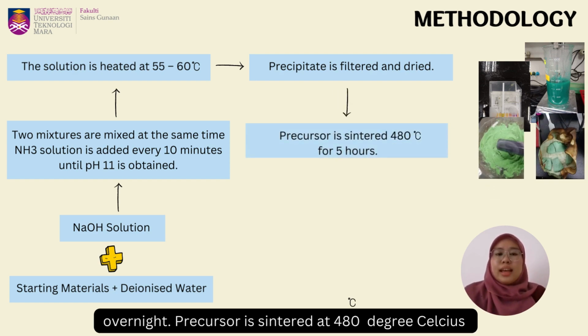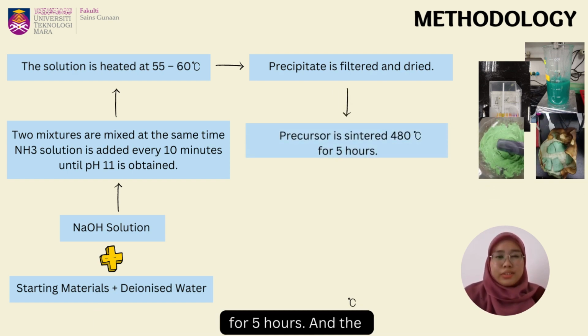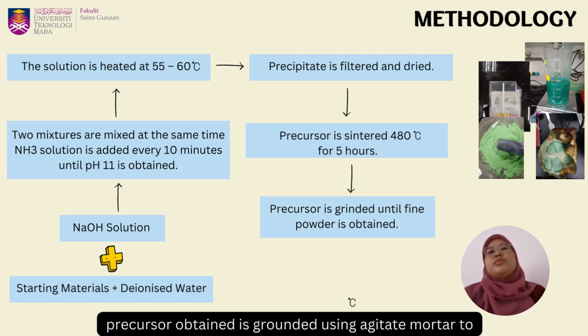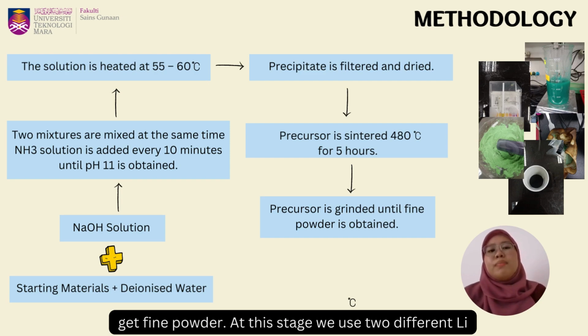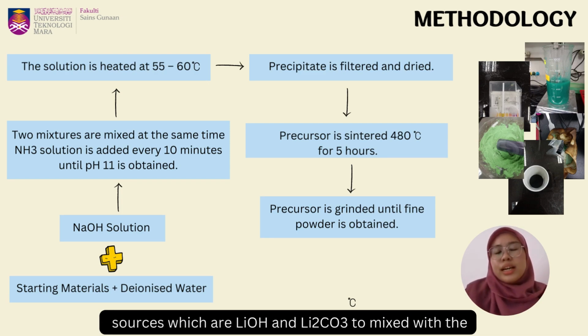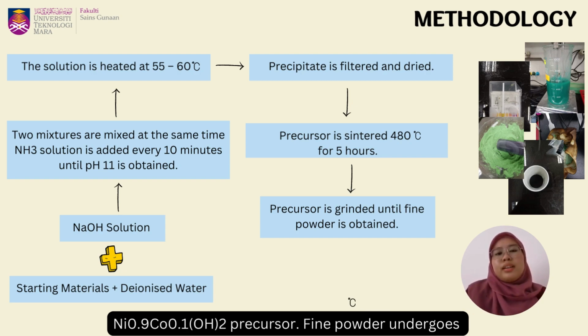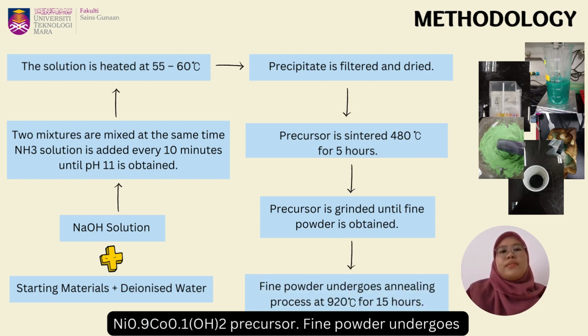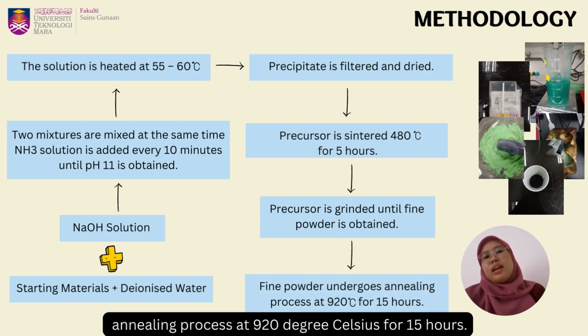The precursor is sintered at 480 degrees Celsius for 5 hours, and the precursor is ground using an agate mortar to get fine powders. At this stage, we use two different lithium sources, which are lithium hydroxide and lithium carbonate, to mix with the nickel cobalt hydroxide precursor. Fine powders undergo an annealing process at 920 degrees Celsius for 15 hours.